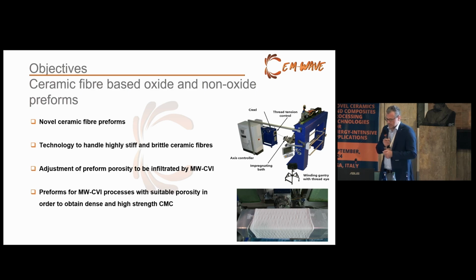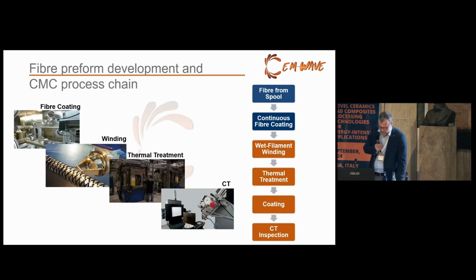In the case of the aluminum oxide, when you slowly change the slurry composition, and you can also change the angle of silicon carbide and aluminum oxide fibers deposit, and it's quite a nice technique to do.